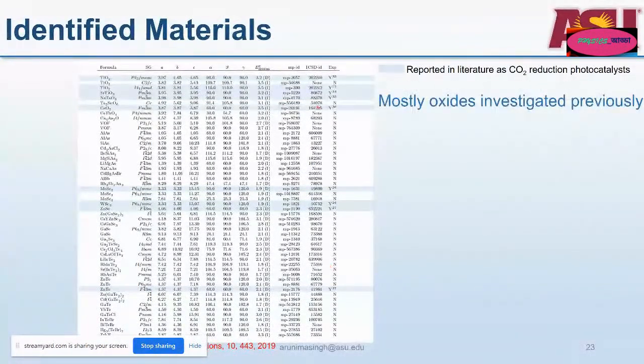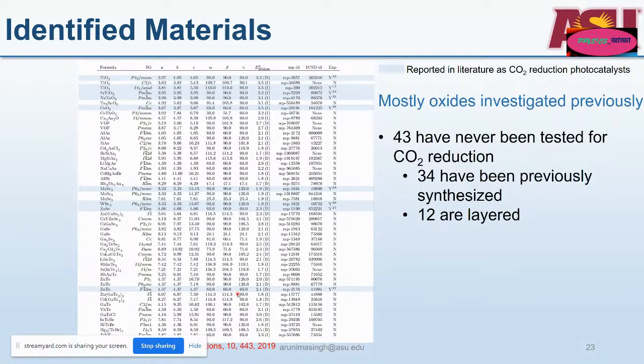And these are mostly oxide materials, the ones at the top. And you can see there's a few selenides and a telluride which has been studied before. What you would find interesting is that out of these 43 materials which have never been tested for CO2 reduction, 34 of them actually have been synthesized for another application before. That means all of these materials are not hypothetical materials. There are actually 34 of them where the recipe for their synthesis is known. So you could actually go to your lab and perhaps synthesize them and test them for CO2 reduction.